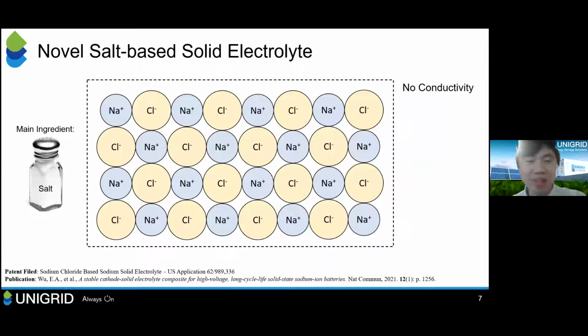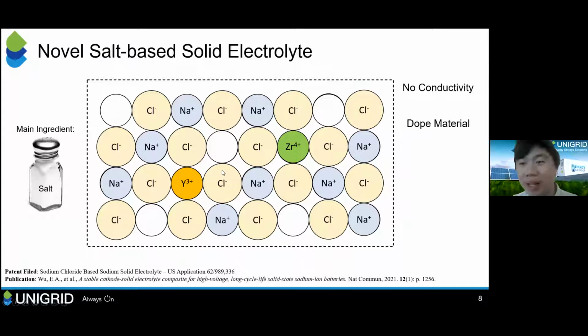So we have to make chemical changes to it. What we do is we first take this material and we dope it with some kind of aliovalent substituent, or a transition metal with a high valence state. I'm just using an example such as zirconium 4+ or yttrium 3+. Now, because they have very different charge numbers, this will cause a charge imbalance in our entire system, and we are forced to remove some sodium in order to balance this charge. In other words, just by doping this into our sodium chloride structure, we have created vacancies in the structure, through which the sodium can now diffuse.